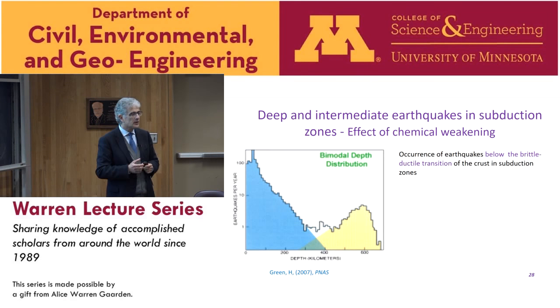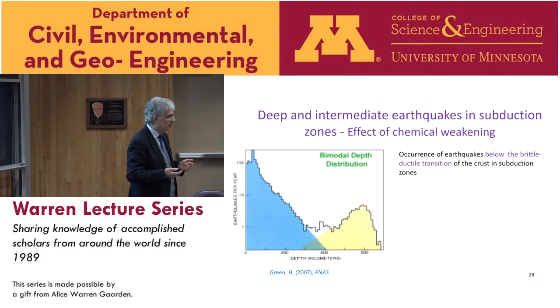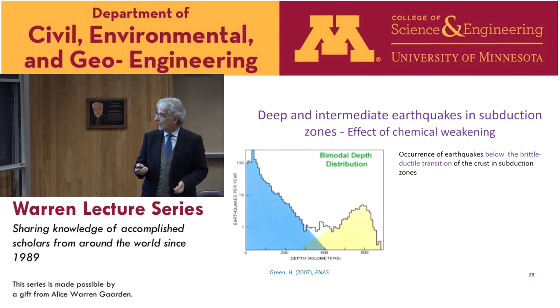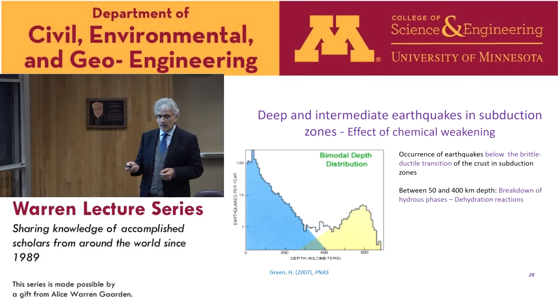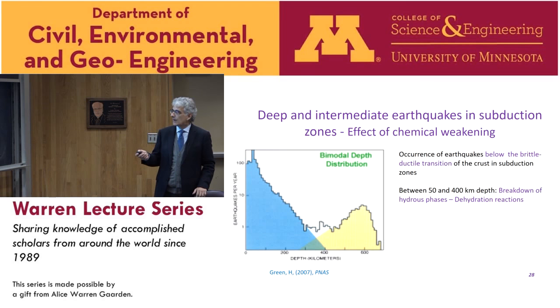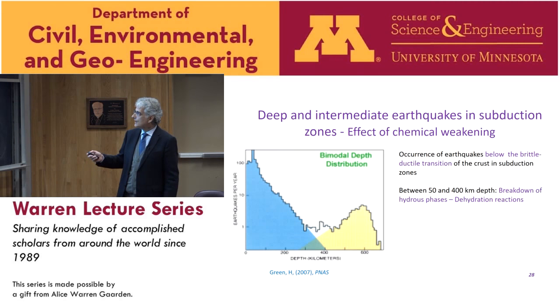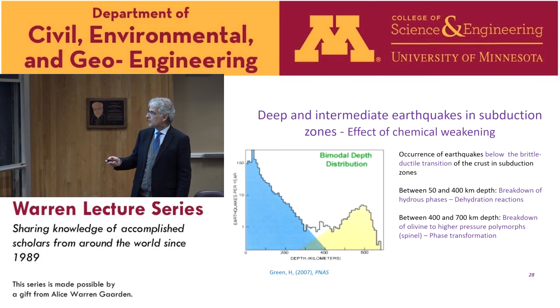And these deep earthquakes were recognized about one century ago, and it was a big paradox. How can we have earthquakes in a ductile regime? And this was explained some years ago, with many studies in the last 20 years about the effect of chemical reactions. So now we understand that between 50 and 400 kilometer depth, these earthquakes are due to dehydration reactions, so breakdown of hydrous phases, and deeper, between 400 and 700 kilometer depth, they are conditions for which we have phase transition of olivine to a higher order polymorph, spinel. And this is accompanied by a change of volume. And this is the mechanism that can trigger an earthquake.